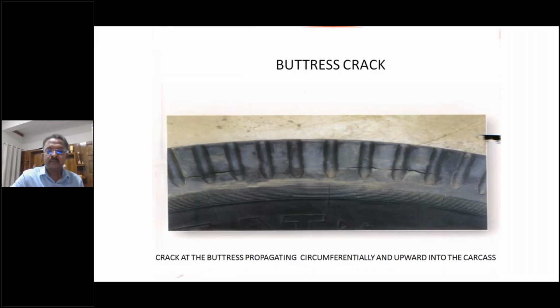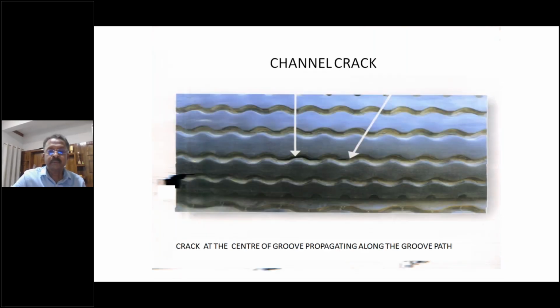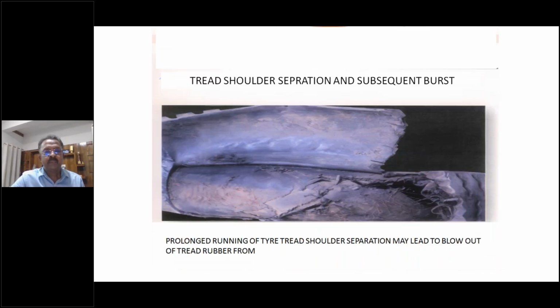Buttress crack: the crack develops at the buttress of the tire. Channel crack is the main complaint for retread rubbers. A crack develops in the groove and propagates around the entire circumference of the tire, and finally the tire gets separated. Then tread shoulder separation and subsequent burst: if shoulder separation is not noticed, the tire will subsequently burst.